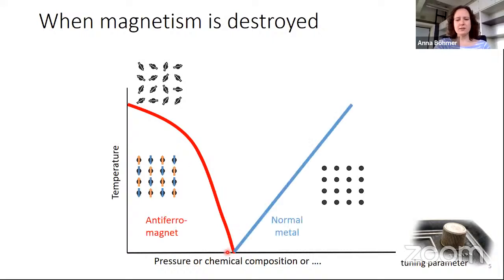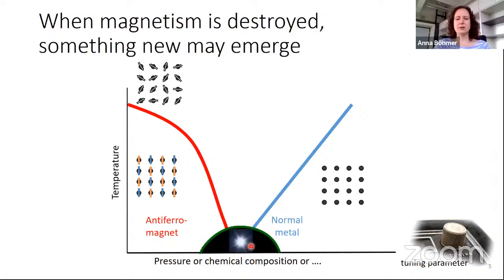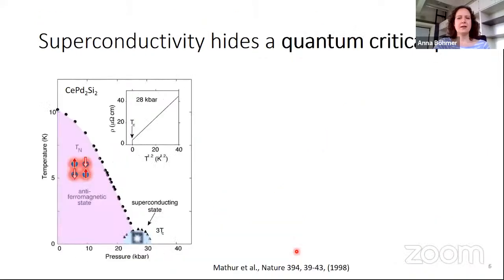You can tune it further and we can tune it to 0. And when we do that, what we find on the other side, well, you typically find normal metal. And the point that's interesting is here. Here the material doesn't really know what it should be. Should it be a magnet or not? And usually it decides to do something else completely. Here's where new phases can emerge. And one of these could be, or is, superconductivity.